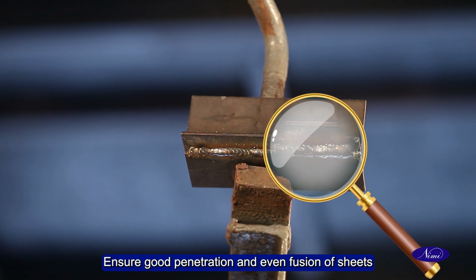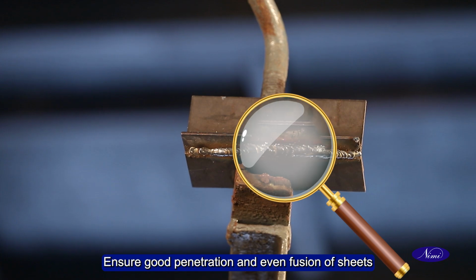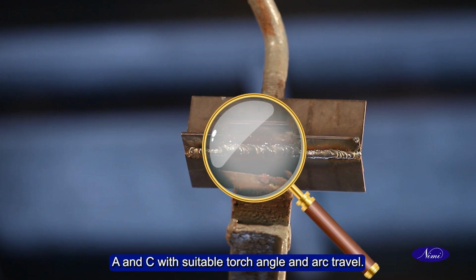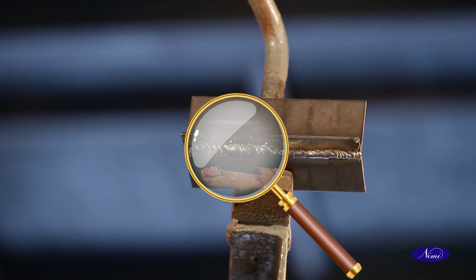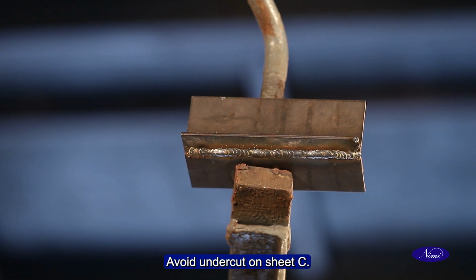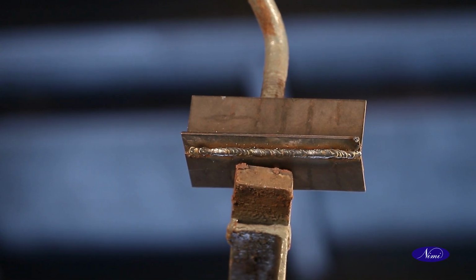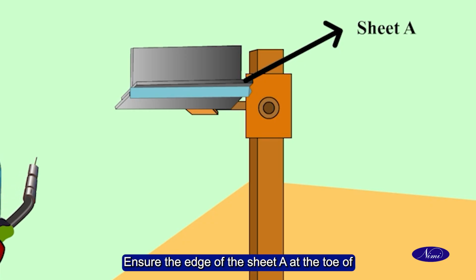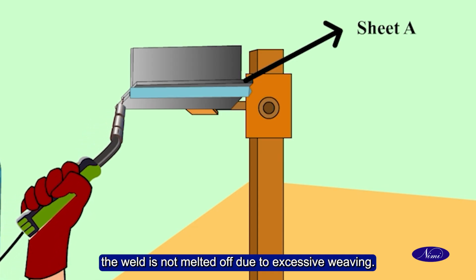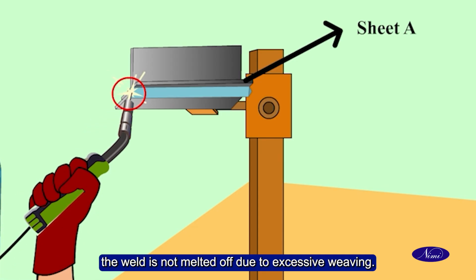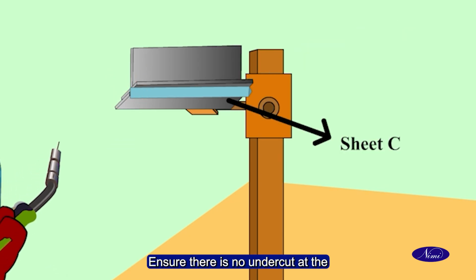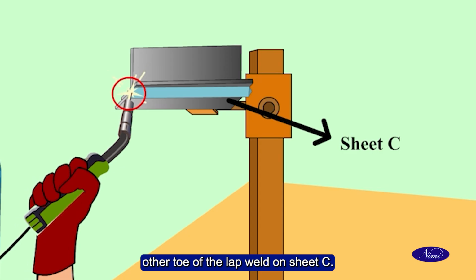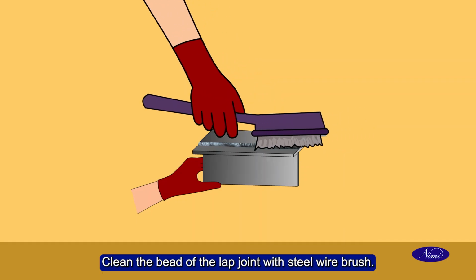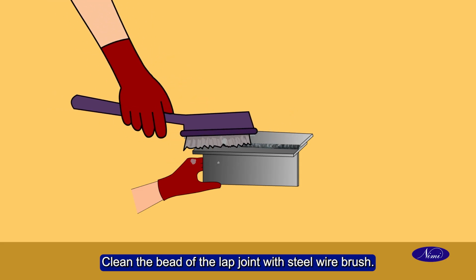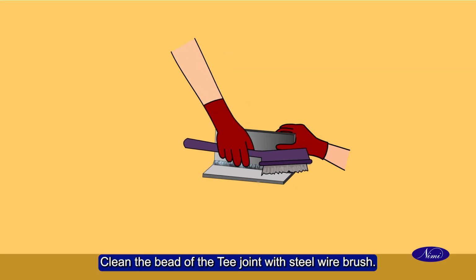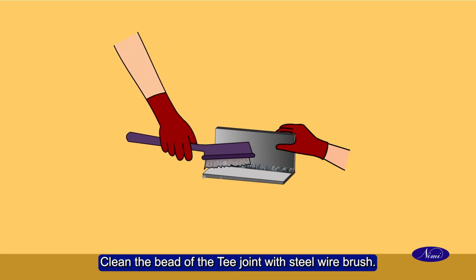Ensure good penetration and even fusion of sheets A and C with suitable torch angle and arc travel. Avoid undercut on sheet C. Ensure the edge of the sheet A at the toe of the weld is not melted off due to excessive weaving. Ensure there is no undercut at the other toe of the lap weld on sheet C. Clean the bead of the lap joint with steel wire brush. Clean the bead of the T-joint with steel wire brush.